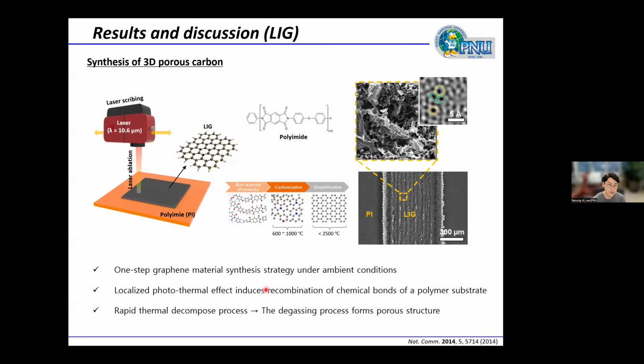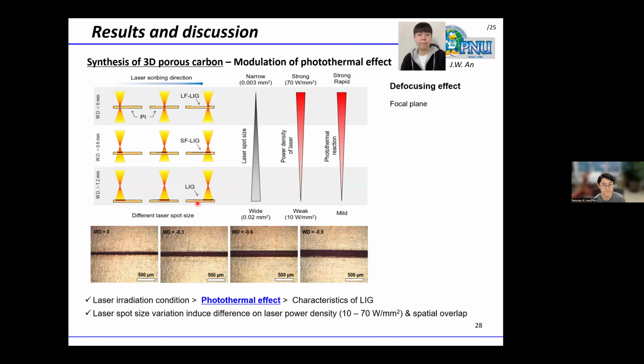Professor Spiros already mentioned this material. This material is called laser-induced graphene, LIG. It is typically synthesized by laser-induced heat treatment of polymer substrates such as polyimide. Because the thermal decomposition reaction is rapid, gases generated during the carbonization of polyimide form a porous carbon structure, as shown here. In our work, to control the structure of LIG, we tune the power density delivered to the polyimide by adjusting the focal length of the laser.